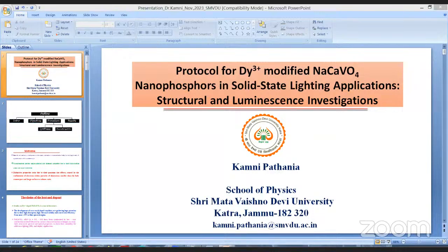These are the various characterization techniques that we have employed: energy dispersive X-ray spectroscopy to look at the chemical composition, X-ray powder diffraction to check for the particle size and phase confirmation, scanning electron microscopy for surface morphology, transmission electron microscopy for particle size and surface morphology, UV-vis spectroscopy to find out the band gap and Urbach energy, and the PL spectroscopy to find out the emission and the excitation spectra.